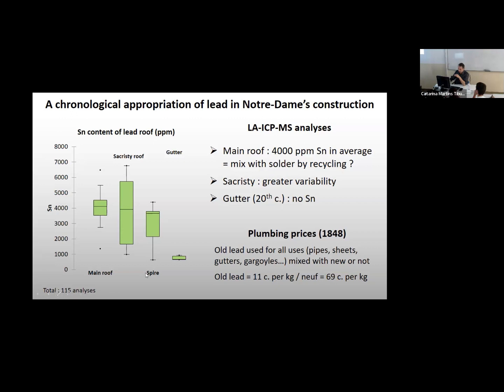And what we see here is for all the upper parts, the spire, but a bit less the spire, but mainly the sacristy roof, and mainly the main roof actually, that there are about 4,000 ppm, that is 0.4% of tin, which is much more than nothing. In comparison with a gutter from the 20th century, which is new lead here, which has almost nothing. So that's one clue that shows that probably here what the archives say is true about recycling of lead in the structure. Here I give some prices which show you that at that time it was profitable to get some old lead, even if it was old lead coming from another monument. It was much cheaper than new lead.